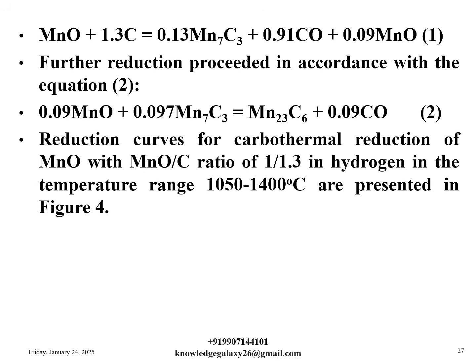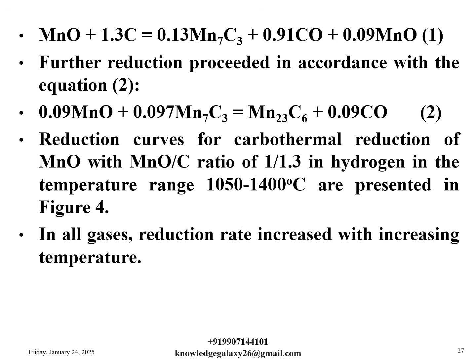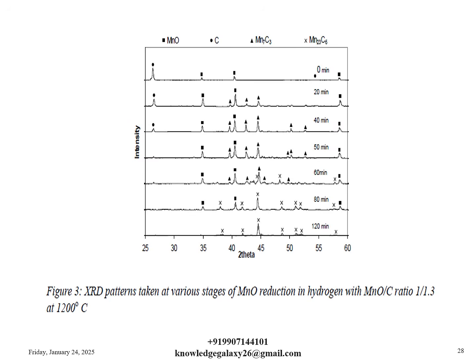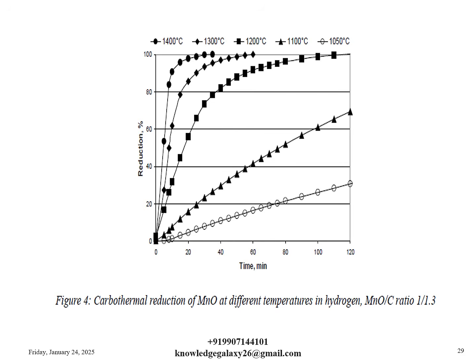Reduction curves for carbothermal reduction of MnO with MnO by C ratio of 1 by 1.3 in hydrogen in the temperature range of 1050 to 1400 degrees Celsius are presented in figure 4 in the coming slide. In all gases, reduction rate increased with increasing temperature. So this is figure 3, which shows the XRD patterns taken at various stages of MnO reduction in hydrogen with MnO by C ratio 1 by 1.3 at 1200 degrees Celsius, which I have just mentioned. And this is figure 4, which shows the carbothermal reduction of MnO at different temperatures in hydrogen having the MnO by C ratio of 1 by 1.3. You can pause the video and observe the different graphs and their pattern, how it is moving.